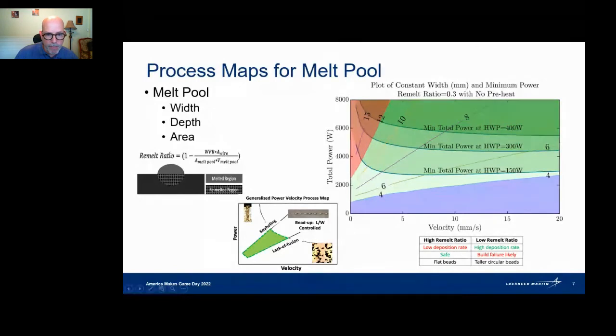What you see here is that Jack Buth and his team have defined what they call a remelt ratio. Depending on the process parameters, how much energy you're dumping into the material, as well as how quickly you're feeding material into the melt pool, you will remelt some of the material in the substrate or the previous builds, and then you'll add some melted material. Jack's come up with a formulation for remelt ratio. And then he developed these process maps. The essential part of these process maps, and they are color coded, and you might guess the red section is a place where you actually don't want to be, and the highlighted green sections are really what I'd call the sweet spot. So what we've been able to do is, through a variety of experiments, a DOE, if you will, on the more relevant process parameters: the total power, the velocity, which is the travel speed, and the wire feed rate.